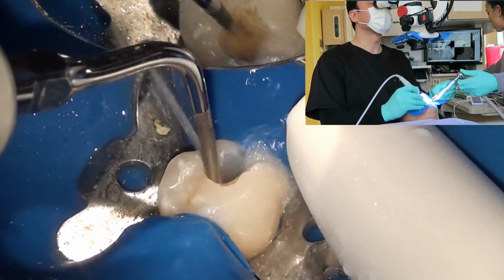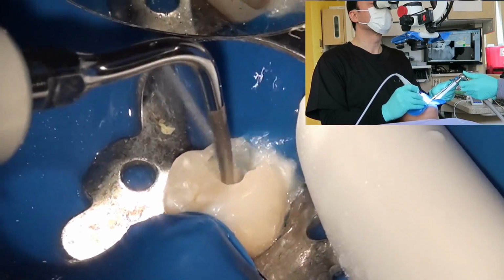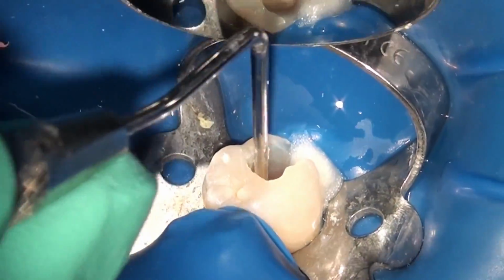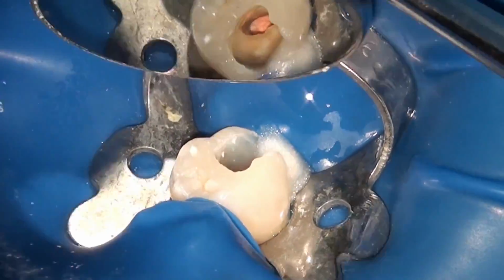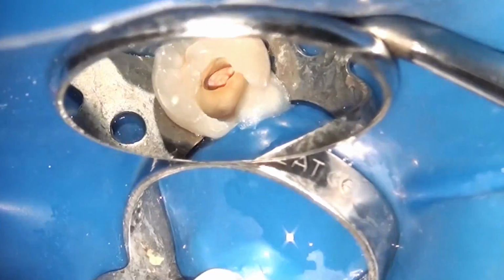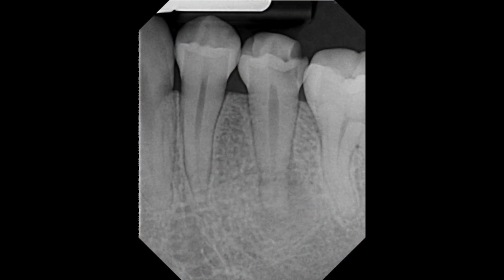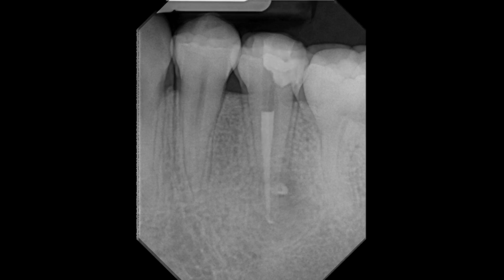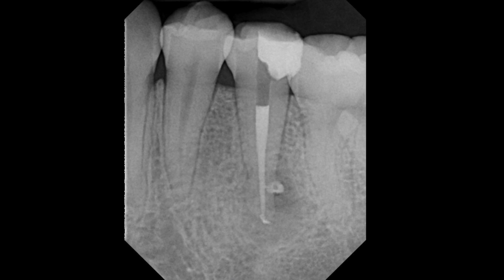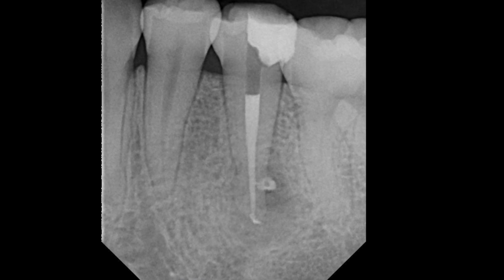And by doing that, then you can clean out the sealer that is remaining using ultrasonic and water, and you're now left with only an interface of gutta percha without any fresh sealer showing. This allows you then to place your core immediately, or in my case, I basically send the patient back to the restorative dentist, and you can see here the final film showing that hydraulic condensation using BC sealer allowed us to pop this lateral canal and do very efficient obturation in this particular case.